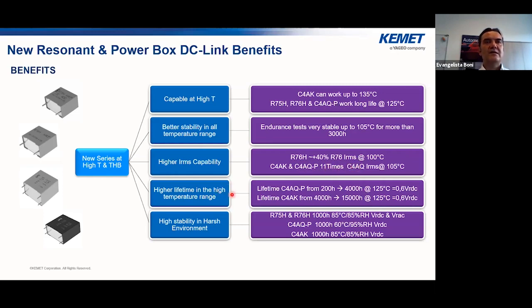And the lifetime we have already spoken about in the previous slide, that we have a really great achievement, especially at higher temperature. But what is important is also the high stability in harsh environment. So these series are also stable in a very harsh environment situation. So R75H, R76H are capable of 85-85 rated voltage, 1,000 hours. C4AQ-P at 60-95, 1,000 hours. C4AK also 85-85, 1,000 hours.